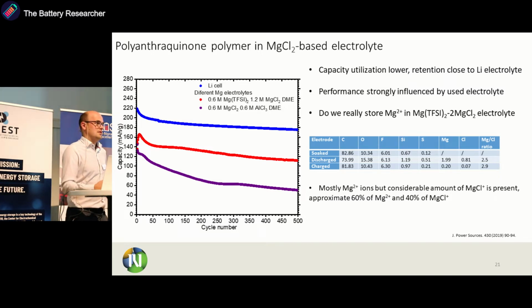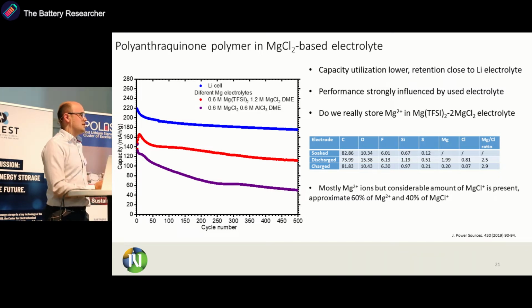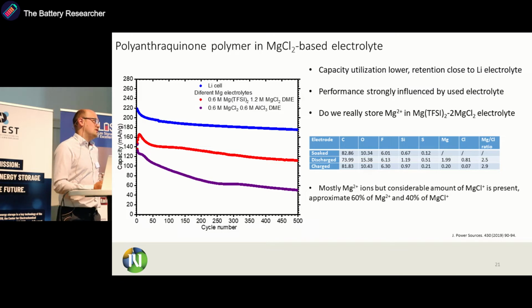So this is somehow not really good, because we are utilizing the salt. It means that if we would want to build a really high energy density battery, we would need to have a considerable amount of electrolyte there.